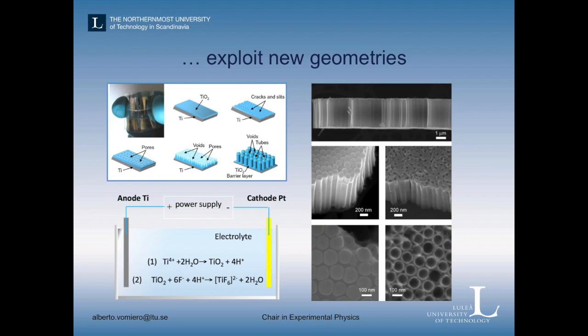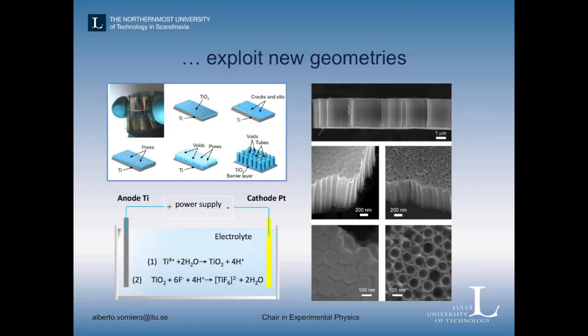And we were able to do that by depositing titanium oxide nanotubes on a plastic substrate. The good point for using these kinds of tubes compared to the nanoparticles is that when you put together nanoparticles, you have to heat them at around 500 degrees to sinter them and to obtain the film you want. While if you grow these nanotubes, they are already ordered after the synthesis, and you don't need a post-heating treatment that can destroy your plastic. So you can get a plastic substrate with an operating solar cell, almost working.